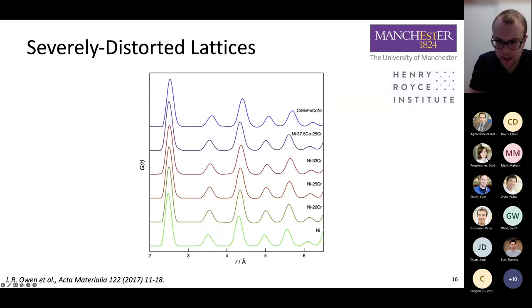However, when you account for things like the fact that the melting point will increase in this direction, so will decrease down here. So in other words, this is going to have greater thermal vibrations going on in the structure. The effect really is not a strong one.